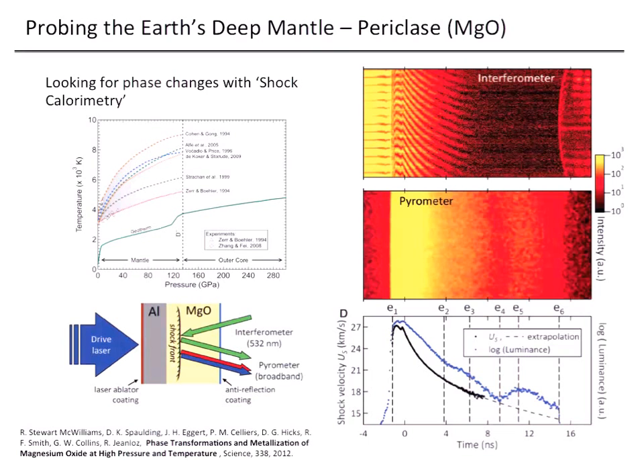It turns out that pyrometry turns out to be a sensitive way of looking for phase changes. You can think of it almost as shock calorimetry, because subtle changes in the intensities of the self-emission often reveal things that the kinematic variables, the shock velocity, don't necessarily show you. And in the case of MgO, that was the case.